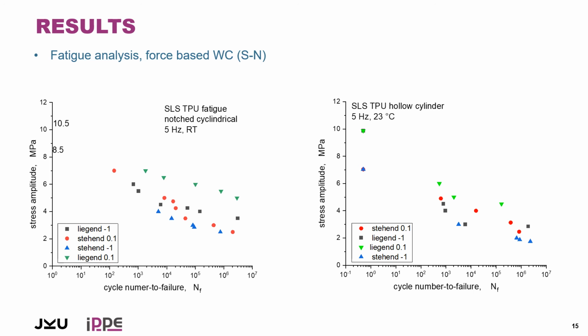The specimens parallel with the stress ratio 0.1 revealed the highest stress values. Then the other specimens, perpendicular or 90 degree and -1, revealed the lowest fatigue resistance. You can fit then the curves if you want with conventional methods. You can use Basquin or any other model. At the moment, we are focusing on the experimental determination or estimation of the durability limit value in the range of up to 5 million cycles in order to give information then for long-term behavior.